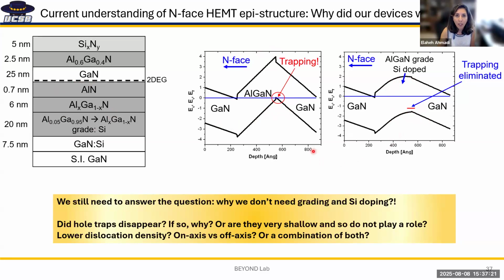Now, the question is why we don't need that now in our MBE grown materials that are on bulk GaN. Did hole traps disappear, or is it that their density significantly reduced? And by the way, this has been attributed to nitrogen vacancies at these interfaces. And is the reason on-axis versus off-axis, or a low dislocation density, or a combination of both? We don't understand yet. And as I said, this is something we are studying.